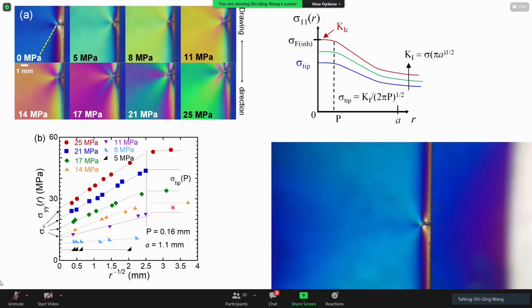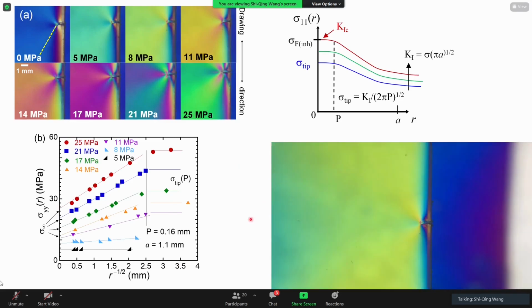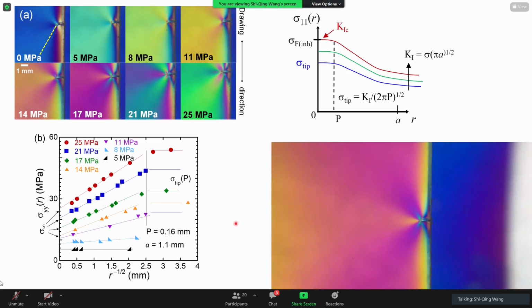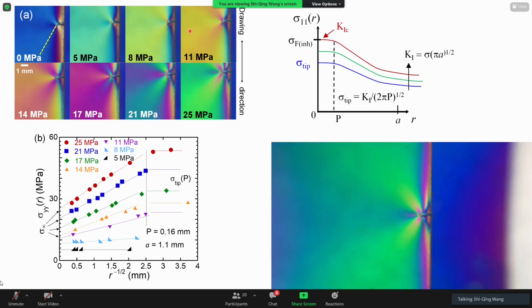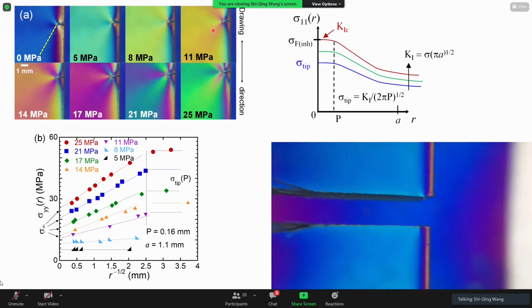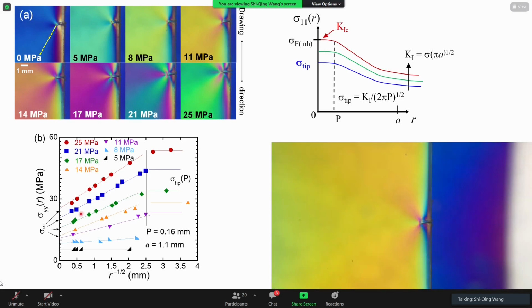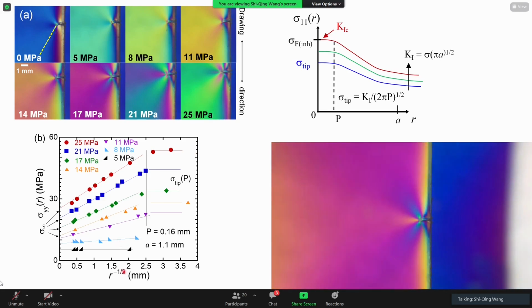So we'll look at PMMA. It's rather challenging to do because the birefringence of PMMA is rather low, so we have to use rather thick samples. But we succeeded in resolving the distribution of birefringence at the tip and converting that back to stress, and plotting that stress as a function, for example, of the reciprocal square root of the distance to the tip. So this is the data. This data confirms a schematic plot like this.